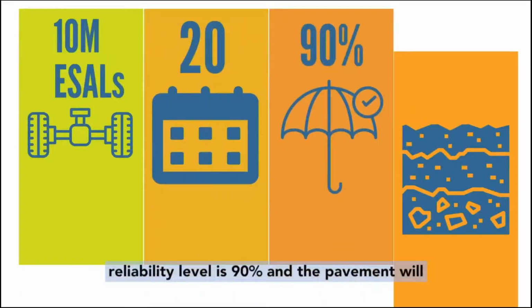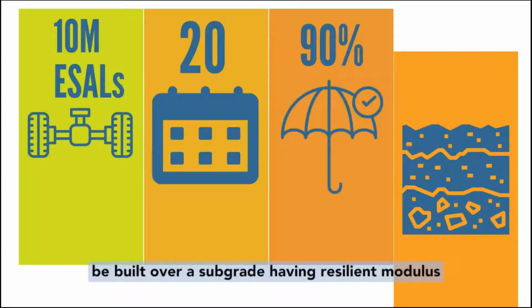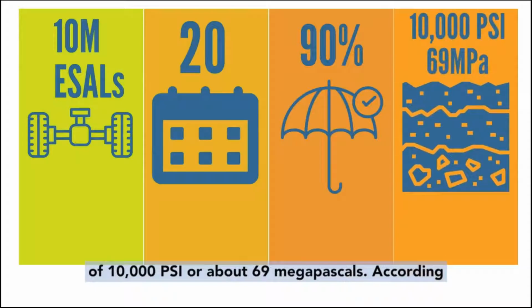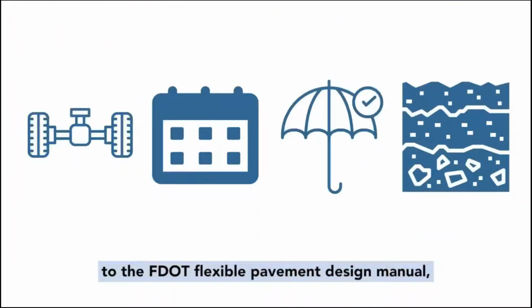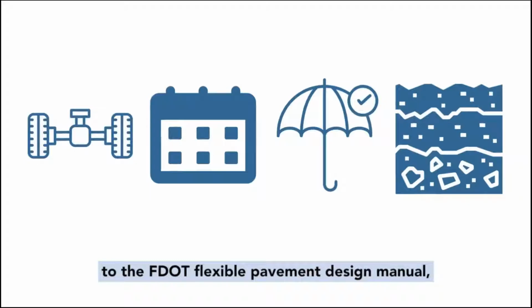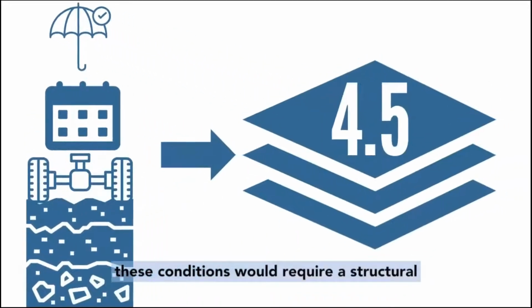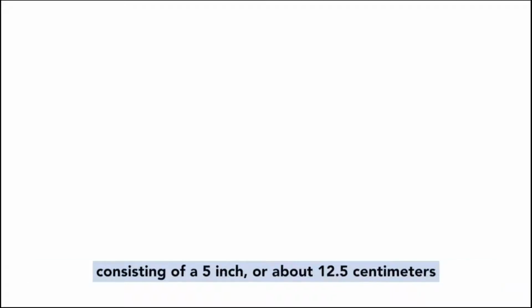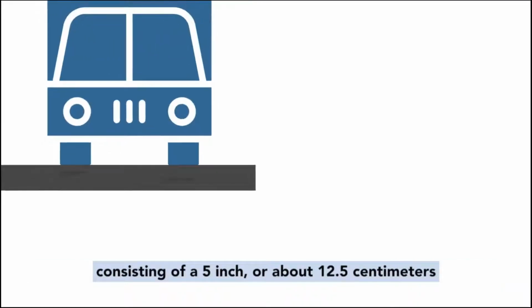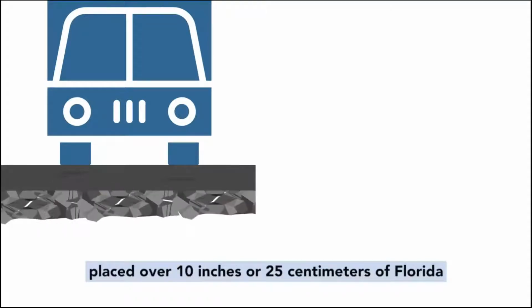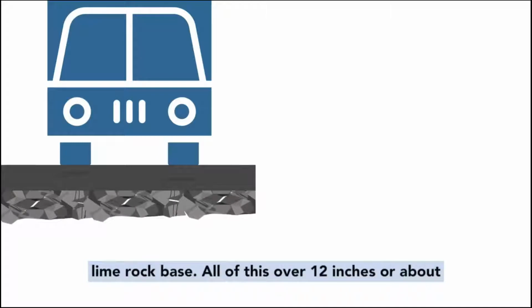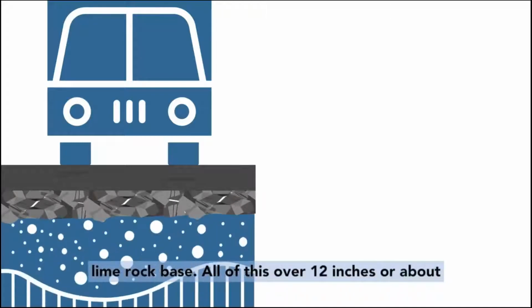The design reliability level is 90%, and the pavement will be built over a subgrade having a resilient modulus of 10,000 psi, or about 69 megapascals. According to the FDOT Flexible Pavement Design Manual, these conditions would require a structural number of 4.50. This would be satisfied by a pavement structure consisting of a 5-inch or about 12.5 centimeters of hot mix asphalt using a conventional binder, placed over 10 inches or 25 centimeters of Florida lime rock base, all of this over 12 inches or about 30 centimeters of a stabilized subgrade.